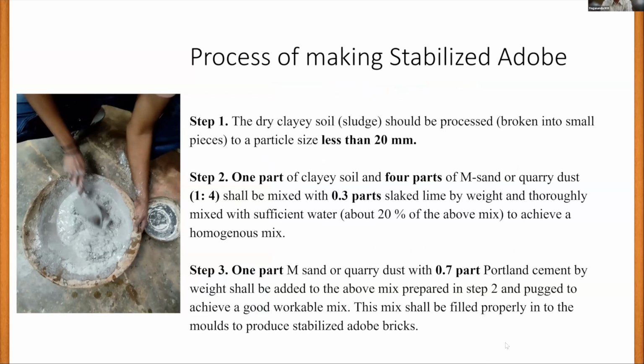Then the process, this is the mix proportion, the process of making stabilized adobe, how we have to use it to make specimens in terms of stabilized adobe brick. The dry clay soil, that is the sludge, should be processed, broken into small pieces, less than 20 mm. Then one part of the clayey soil to four parts of sand or quarry dust can be mixed with 0.3 parts of slaked lime or calcium hydroxide by weight and thoroughly mixed with sufficient water, about 20% or more, to achieve a homogeneous mix. This is the critical part of it, because you need to wet the clay. It has to soften. Only then it is available for mixing.